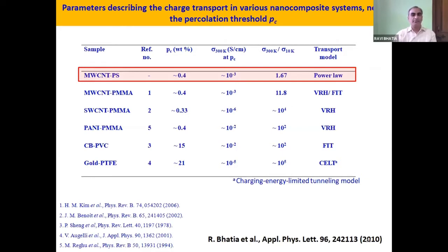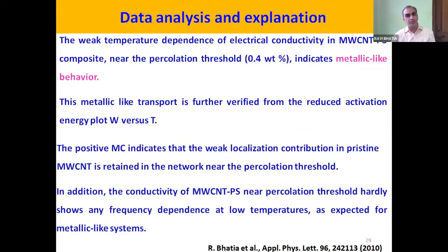So until you have shown the sample quality in terms of its characterization, one should not go for further measurement, because it will give rise to confusion, and it needs to be understood that we must present the true picture of a particular material through our experimentation. So the important feature of this work was a very weak temperature dependence near the percolation threshold, which indicates metallic behavior, which was further verified by the WT graph, and also by magnetoconductance and frequency dependent conductivity.